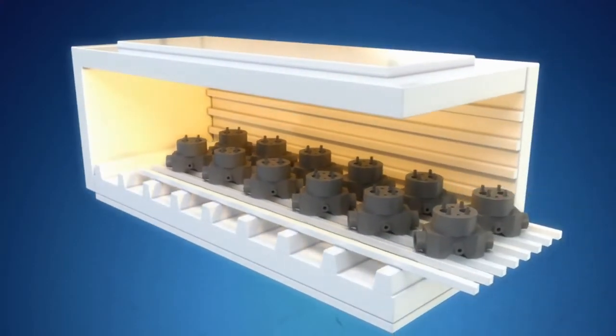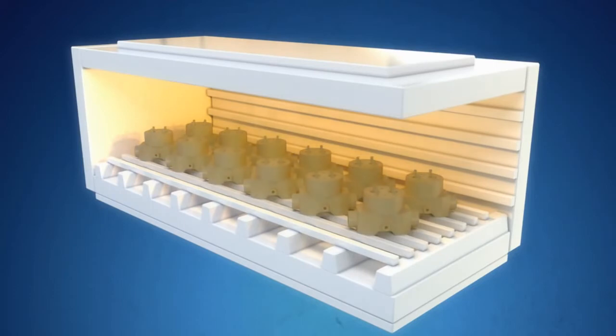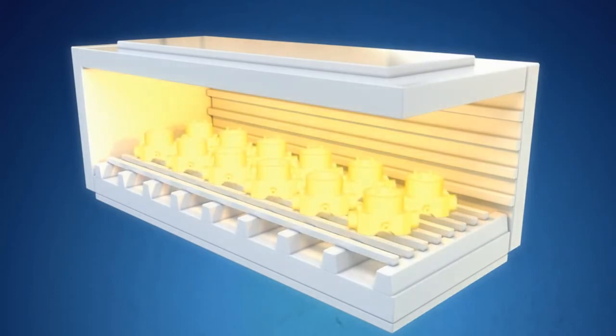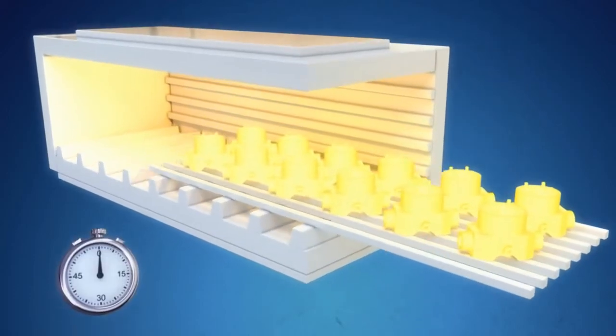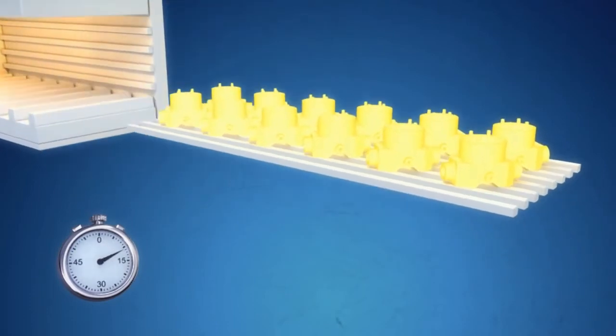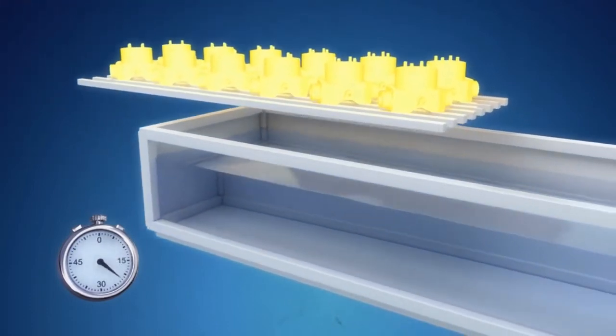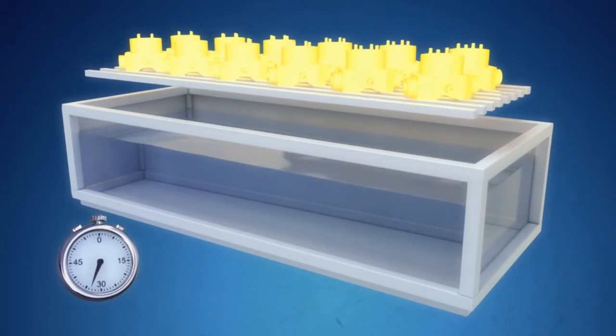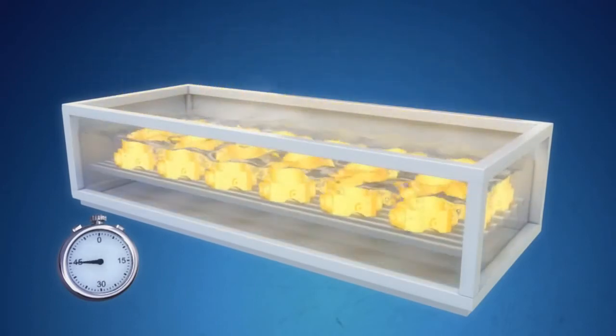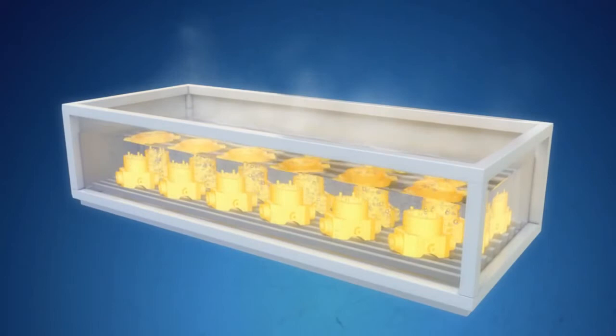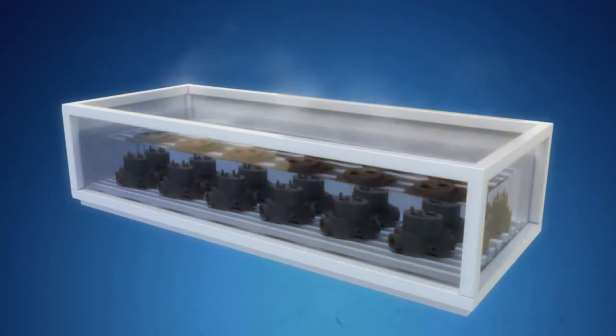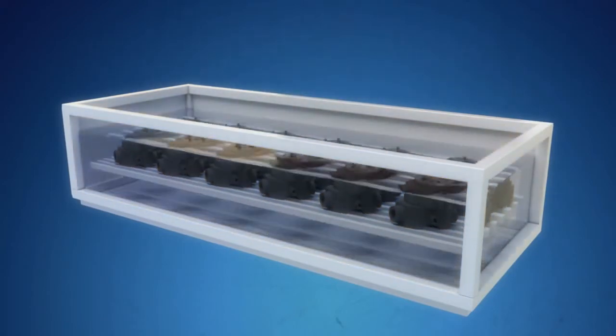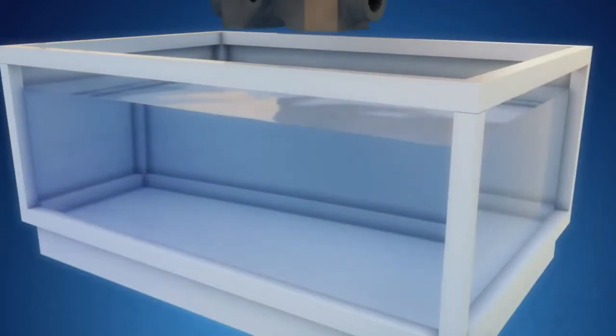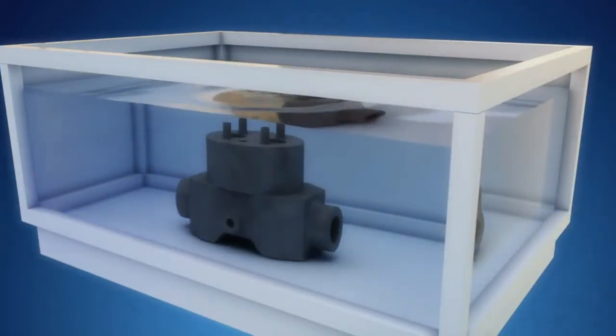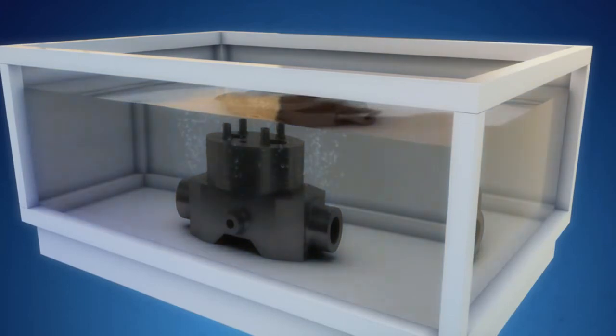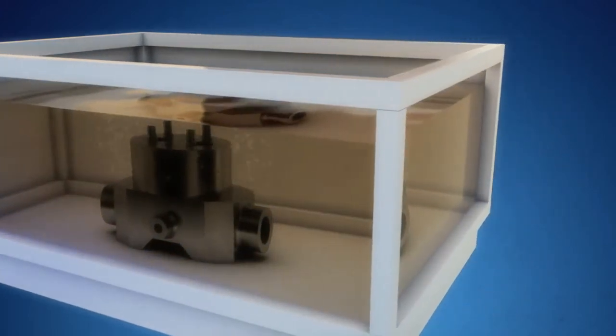The HIPed material is heat-treated in qualified and approved furnaces to obtain correct properties. Rapid cooling is important for many materials to ensure the required properties are attained. After heat treatment and removal of any test material, the part is pickled by submerging the capsule in sulfuric acid, which dissolves the sheet metal.